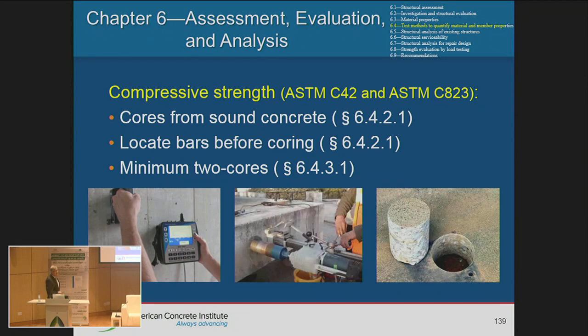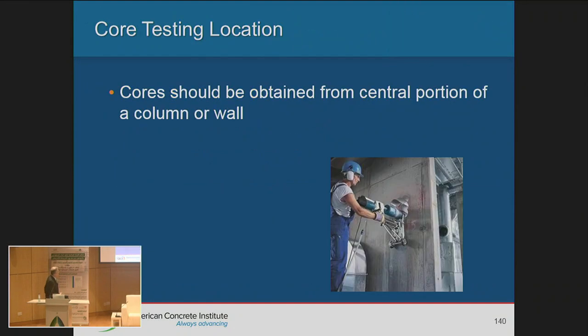So cores have to be taken from sound concrete. If you see a crack, don't try to take your cores where the crack is, thinking, I want to see what's exactly there. No. When you take your cores, take them away from cracks, where you have sound concrete. That's where you take your cores from. Locate your bars before taking your cores. The cores should not include any reinforcement. And when it comes to concrete, use a minimum of 2 cores. And if you take the cores, let's say in a column or wall, where would you take them? From the top, bottom, or from the middle?